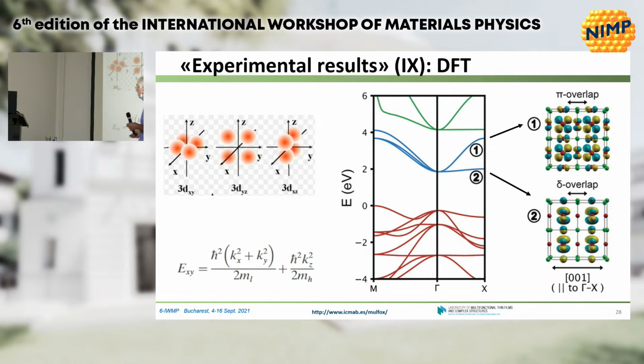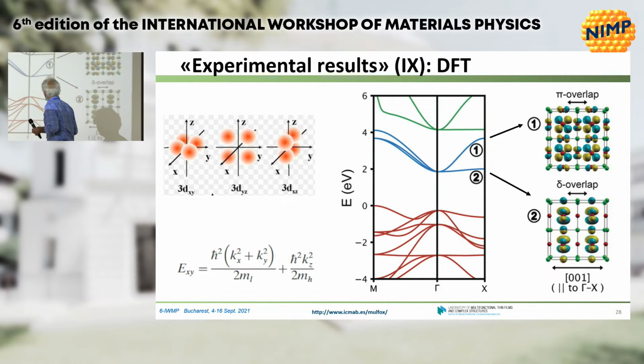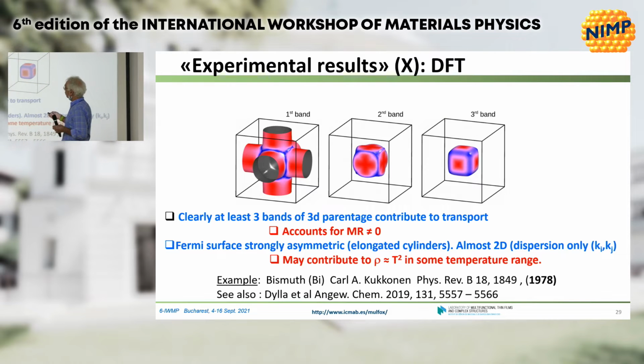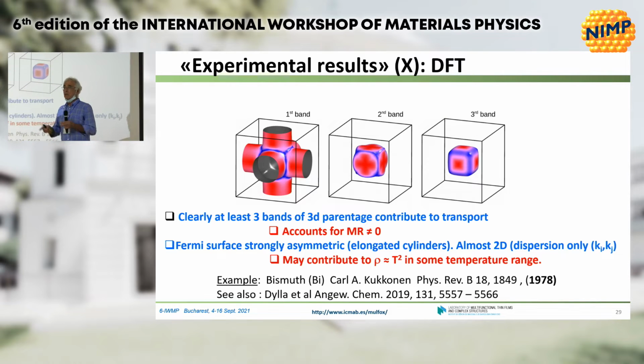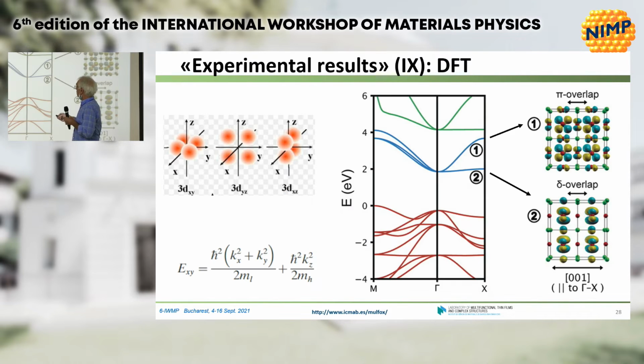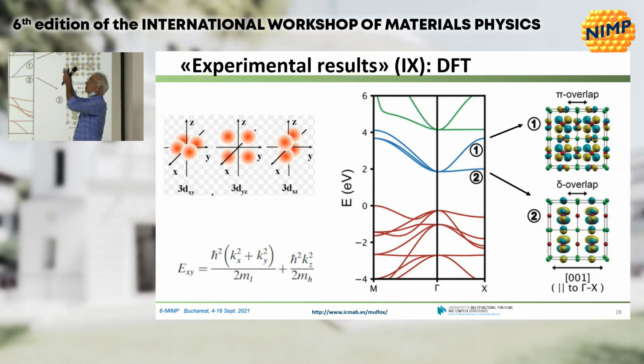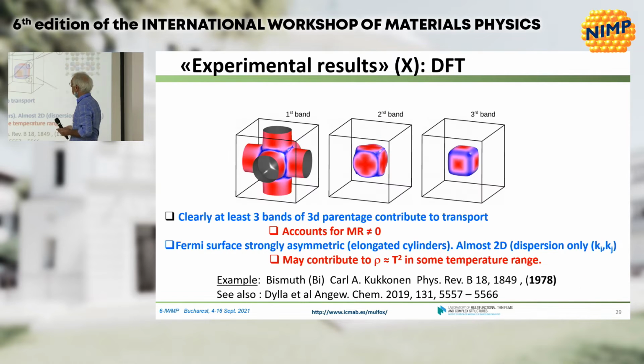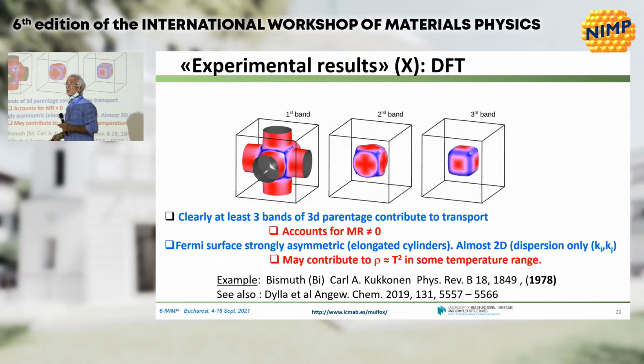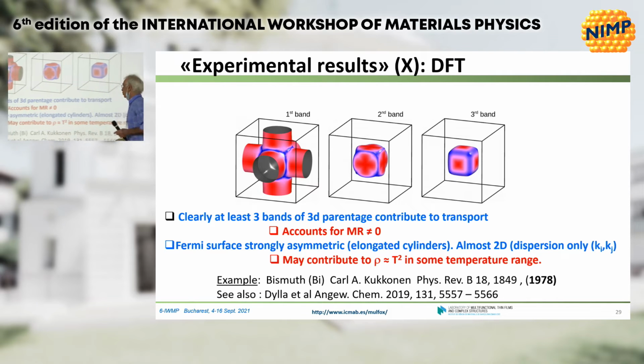In fact, it's the intersection of three different cylinders, because there is only mixing of orbitals in two directions, not in three. There is always one direction in which one orbital is never mixed. So you have one cylinder in one direction, one cylinder in the other, and one in the other. So the Fermi surface is not a sphere, and you see that there are three bands crossing. So it's obvious that magnetoresistance should come. This contribution should always give a magnetoresistance, which we do observe.